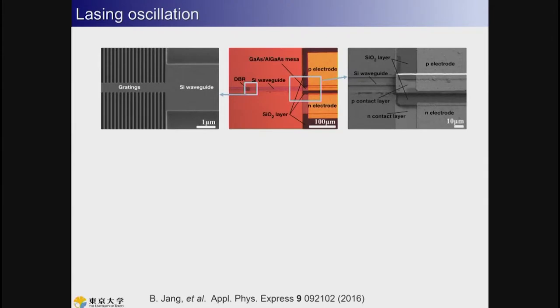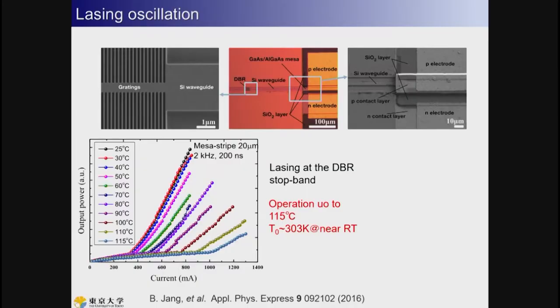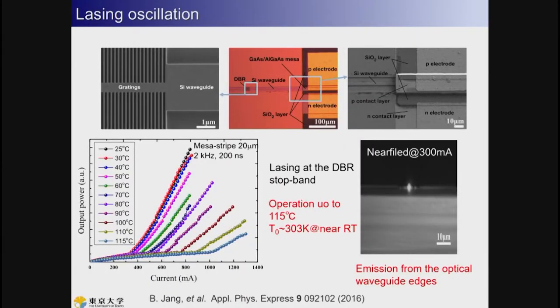Indeed, we have fabricated this evanescent type DBR structure laser with quantum dot gain. We have achieved high temperature operation up to 115 degrees Celsius and so on. T0 is 300 Kelvin near room temperature. And this is a near field pattern observed at a current of 300 milliamps and so on. You can see the emission from the optical waveguide edges.